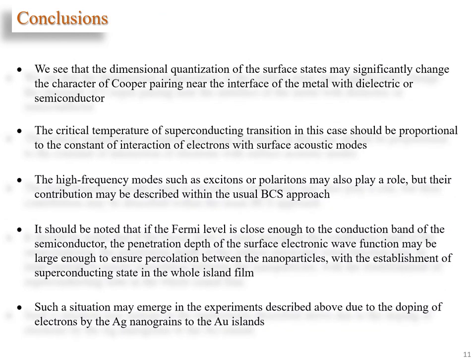Conclusions. We see that the dimensional quantization of the surface states may significantly change the character of Cooper pairing near the interface of the metal. The critical temperature of superconducting transition, in this case, should be proportional to the constant of interaction of electrons with surface acoustic modes. The high frequency modes, such as surface excitons or polaritons, may also play a role, but their contribution may be described within the usual BCS approach.